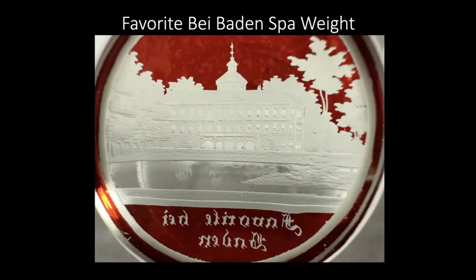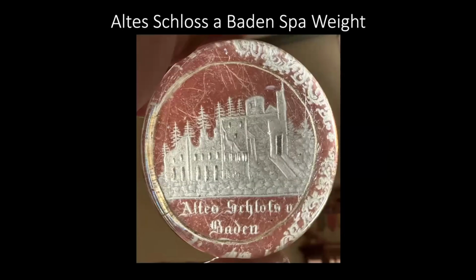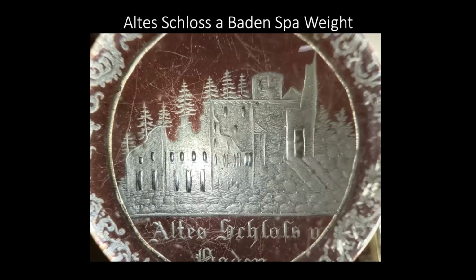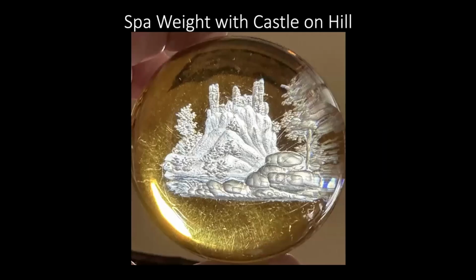Bill and Nancy Barton wrote an article about spa weights for the PCA Bulletin. They reported that in the first half of the 19th century, Frederick Egermann discovered methods for applying salts to produce a stain on the glass after firing. This is another Baden weight. This is the Altes Schloss or Old Castle. There's a little more detail on it. Copper salts were used to produce the red stain. There are also ones with a yellow stain that were produced using silver salts.